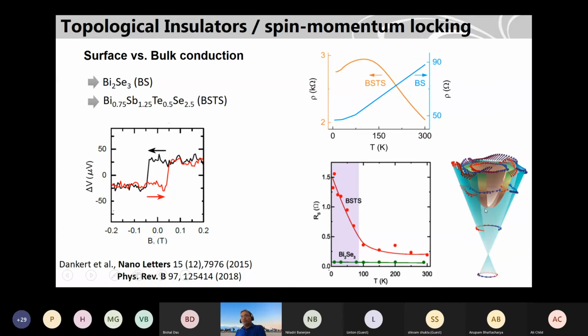But some bulk conduction is also happening in the beginning. Because it's a semiconductor, when you cool down, you freeze out the bulk carriers, because the Fermi level is below the conduction band. When you freeze out all the bulk conduction of the semiconductor below some temperature, whatever remaining conduction is mostly coming from the surface states. So the surface state is more dominating in the transport, and therefore you see this bump-like feature. Two mechanisms are competing. Below some temperature, the surface is more dominating, and above that temperature, more bulk, which is freezing out when you cool down. So carriers are getting frozen. Yeah, I hope it's clear.